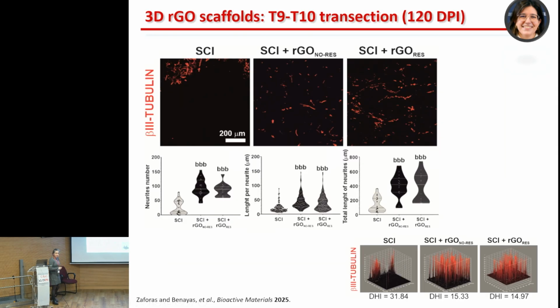Not in the case of the neurites. We also evaluated neurites again inside our scaffold. As you can see here, we obtained a significantly higher number of neurites, length per neurite, and also total length of neurites when we evaluated the lesion in which we implanted our reduced graphene oxide. And not only that, the distribution. Look at these diagrams. As you can see here from the confocal images, we have a nice homogeneous distribution of the neurites all along the lesion site, which is very important because we want to regenerate the entire 3D volume, not only a portion, not only the lateral, the entire.